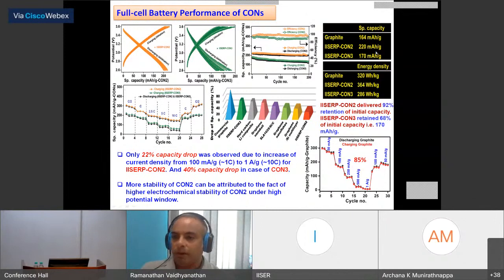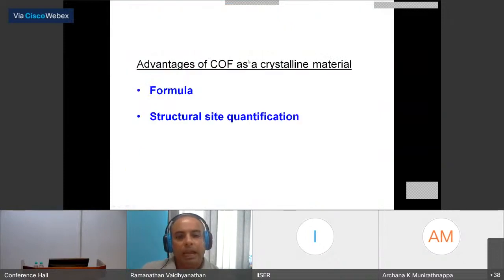And the most important thing, which is a quantifiable value, is the energy density. You can see the energy density of these CON-based batteries is fantastic compared to even the graphite materials. Sorry, I should be pointing out here. This is the CON-based one. So the graphite is giving 164, whereas the CON is able to give a very high value here, 220 milliamp hour per gram.